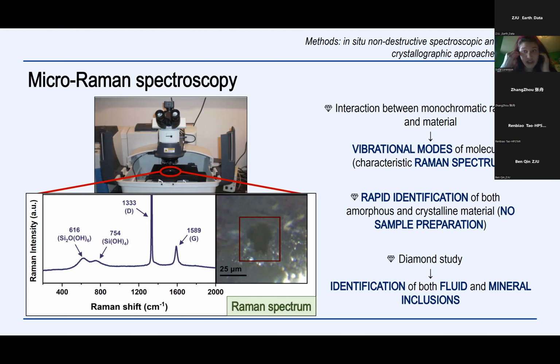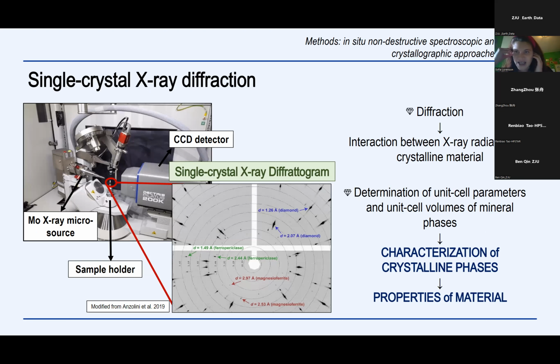Continuing with single crystal X-ray diffraction, this technique, differently from micro-Raman spectroscopy, uses the phenomenon of diffraction, which is due to the interaction between X-ray radiation and crystalline material. This is important because, differently from micro-Raman spectroscopy, single crystal X-ray diffraction, or diffraction in general, allows us to study only crystalline material. The result is, as in this example, a single crystal X-ray diffractogram. As you can see here, we have a series of black spots, and these black spots correspond to the diffracted peaks that we get when a family of crystallographic planes in minerals enters the diffraction condition according to the Bragg law.